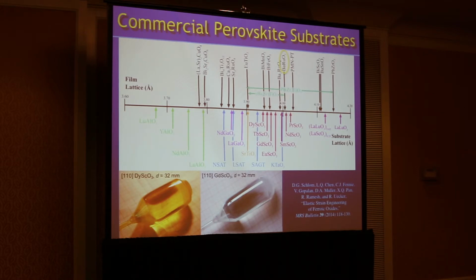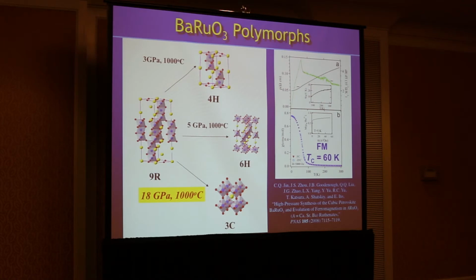Okay, now barium ruthenate exists, and if you ask Mr. Gibbs what the stable form of that is at atmospheric pressure, it's this hexagonal structure shown over here. And the high pressure people have been having lots of fun with barium ruthenate and accessing these hidden ground states, this one at 30,000 atmospheres of pressure, this one at 50,000 atmospheres of pressure, and most recently, this one down here at 180,000 atmospheres of pressure, done by John Goodenough recently. And in this cubic form, indeed, the magnetic properties have changed. So this becomes ferromagnetic. It's got a transition temperature, which Goodenough shows quite nicely.